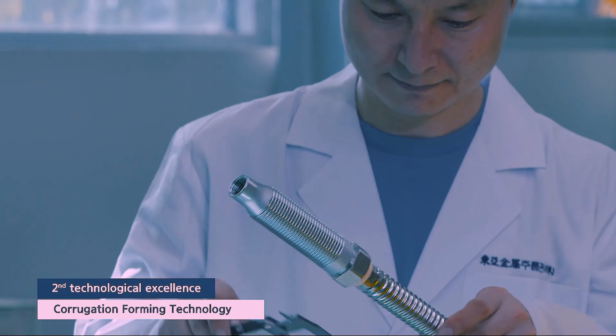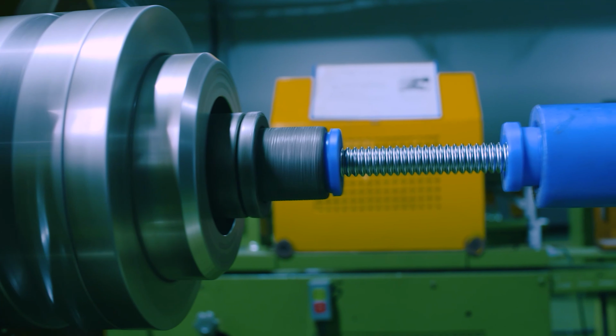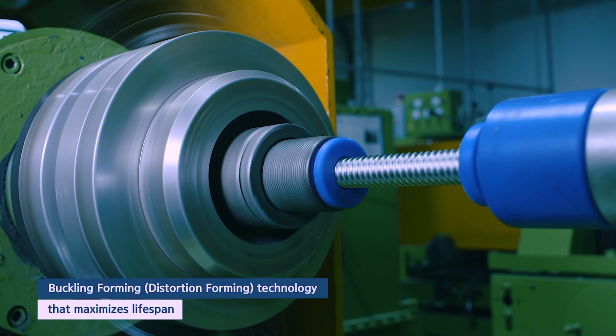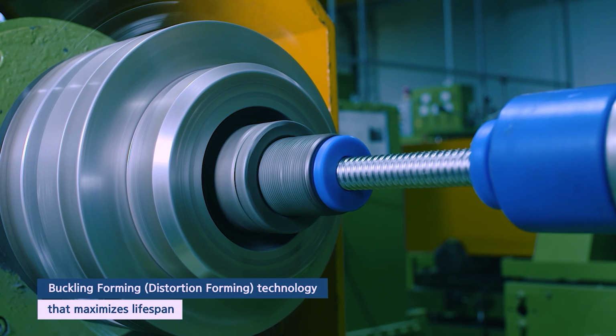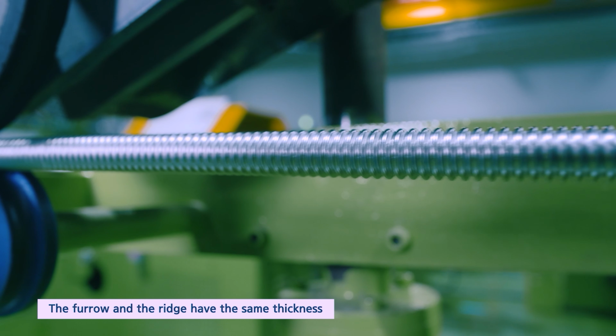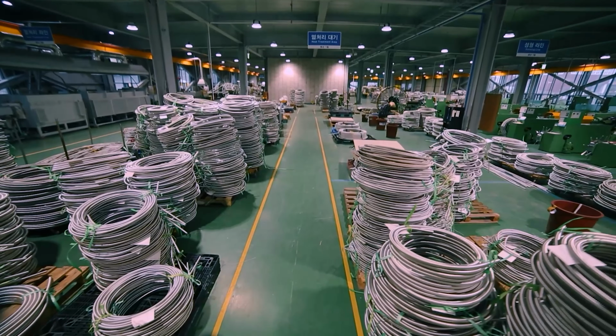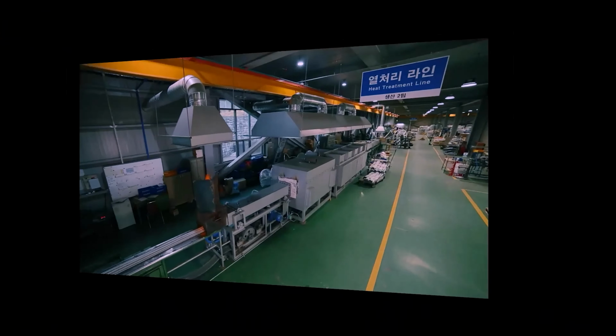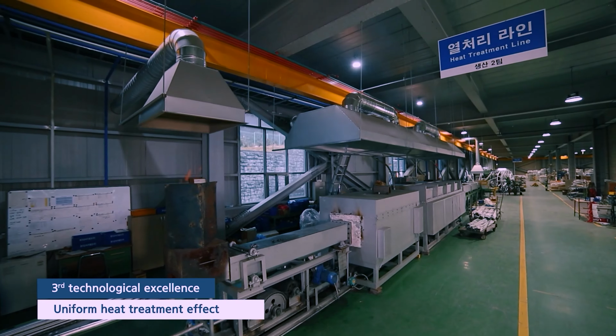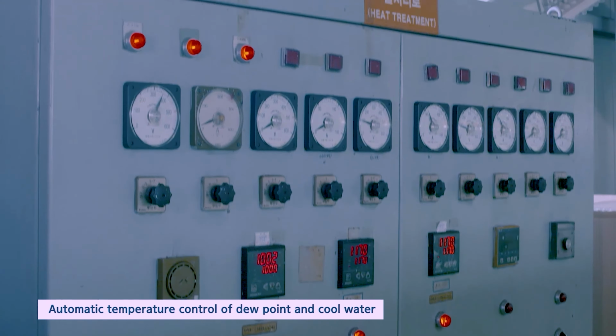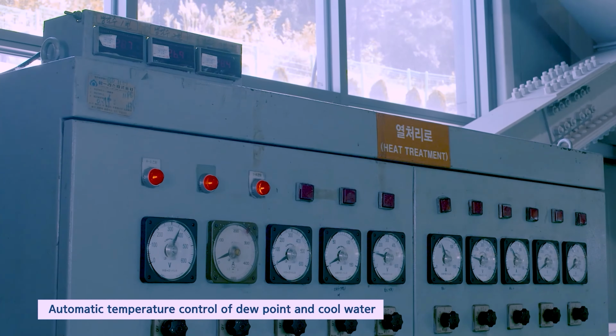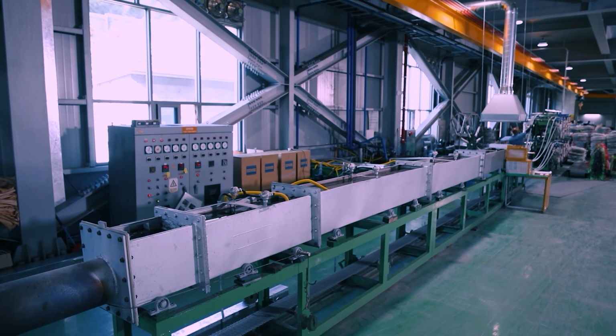To maximize the lifespan of the flexible tubes, a new technology, the buckling forming method, was applied. Under the optimal temperature condition, the corrugation forming is done. The furrow and the ridge show no change in thickness in this world's best CSST. The heat treatment of the flexible tube automatically controls the dew point. It automatically controls the temperature of coolant using a freezer. Regardless of the external temperature condition, according to the coolant temperature set by the engineer, the temperature is controlled automatically and uniformly, so the effect of the heat treatment is also uniform.